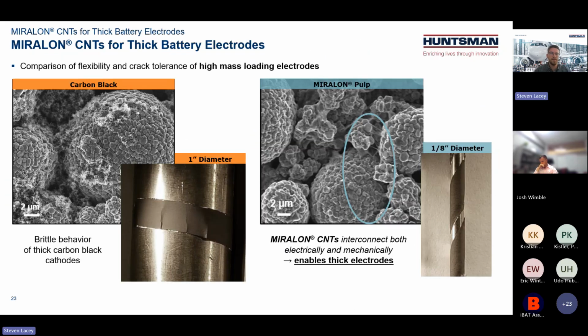Now, another aspect that's innovative and useful for MIRALON carbon nanotubes is the mechanical aspect. So this network structure of tubes also enables mechanical reinforcement of the electrode, which could also enable high mass loading. So in this case, if you have carbon black only and you have a very high mass loading, say almost 30 milligram per centimeter squared, you see noticeable cracking when you wrap it around a dowel rod, so a metal rod in this case, as a qualitative example. However, for MIRALON at the same mass loading, you can go to a much lower diameter and easily wrap the coating around it without any cracking. So this shows that not only do you have electrical pathway improvement, but also mechanical improvement to the electrode.